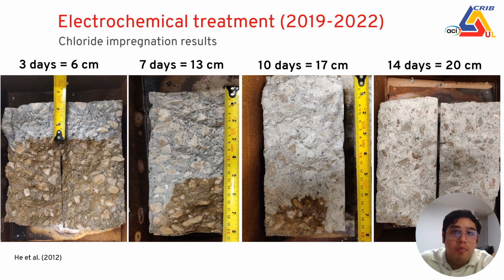Once the setup was properly developed, I had to confirm that the chloride impregnation was done on my specimens. So I started with a non-reactive aggregate to try to migrate chloride to the other end of the specimen. We tried the electrochemical treatment at different times to see at what time we can reach total impregnation of the chloride. As you can see here in the picture, at 3 days, 7 days, 10 days, and 14 days, how the chloride was migrating in my concrete specimens.